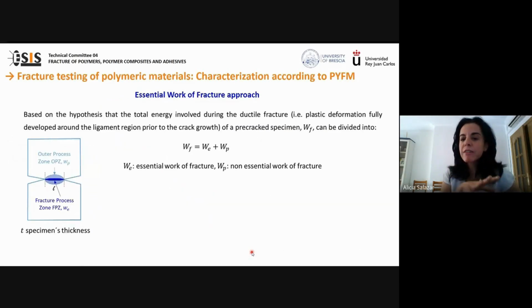The essential work of fracture approach is based on the hypothesis that the total energy involved during the ductile fracture of a cracked film is divided into two terms. The essential work of fracture, WE, that is specific to the fracture of the material in the fracture process zone, shown in dark blue in this plot, and a non-essential work of fracture, WP, which is related to gross plastic deformation occurring outside the fracture process zone and shown in light blue in this plot. This plot shows evidently a cracked film. So the total energy absorbed can be written as follows, where L is the ligament length, T is the sheet thickness, and beta is a shape factor associated with the dimension of the plastic zone in the outer process zone.